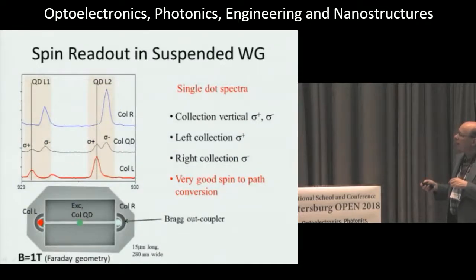So here we now have a nanobeam waveguide, a very simple structure with a quantum dot at the center. We observe vertically first of all, and we see sigma plus and sigma minus components. And then if we detect from the right out coupler, we see just the sigma minus component. And if we detect from the left out coupler, the red curve, we see just the sigma plus component. So in other words, sigma minus goes right and sigma plus goes left. So we've achieved very good spin to path conversion.